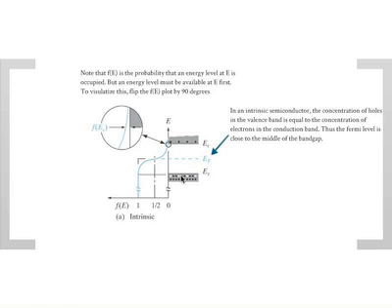But with that caveat, we can say in an intrinsic material, the Fermi level will be very close to the middle of the band. We know that the probability that the energy level there will be occupied by an electron is half, 50%. But of course, there is no energy level there. Right? It's an energy band gap. So there are no electrons there. As simple as that. Although f of E is greater than 0 here, there are no available levels, so no carriers there. We'll quantify this in a second, but I want you again to understand this qualitatively.